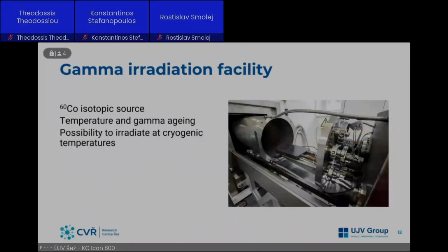A specific part of our infrastructure is not just research reactors as a source of radiation. We also have our gamma irradiation facility, a cobalt-60 isotopic source. Technically, that's not an issue. You can find those in many places, like in Rostock, where they use it for sterilization of wood and other equipment. But in our case, the added value is that we can control the temperature of the irradiation. For example, there were studies of electronic parts meant to go to outer space, which were tested there to see if they survive or not.